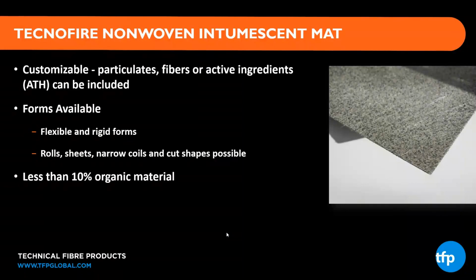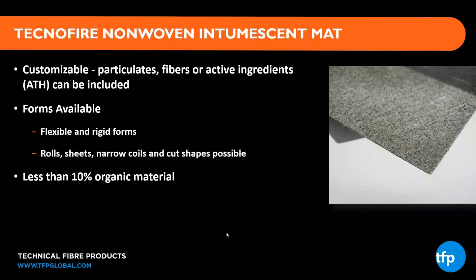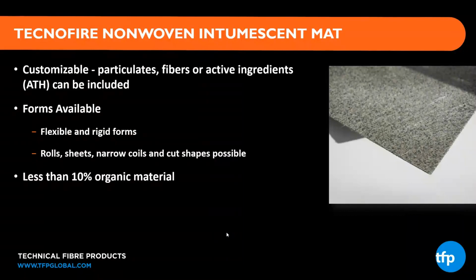It's a very customizable product. Basically in a wet lay process, you're going to mix together a batch of different components and then spill those across a moving wire to dry them out, and you end up with a fabric, a rolled good. So we have the ability to add different fibers and particles into that mix, or look at some different active ingredients, some FR materials. ATH, as Neil referenced earlier, is one of those materials that we can add into our product. We make a few different forms. If you look at that picture on the right, that would be the form that comes off our paper making machines, our non-woven machines. It's more of a fabric. There are flexible and rigid forms.